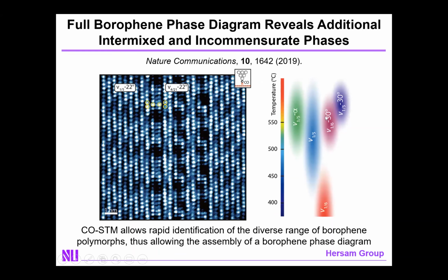V1/5. We also found V1/6 and V1/5 phases that were rotated with respect to the silver lattice. You can also find additional incommensurate phases, such as these that are rotated by 22 degrees with respect to the silver. And it's also possible to form superlattices of different borophene polymorphs, as we see here, where we have mixtures of the V1/6 and V1/5 structure.